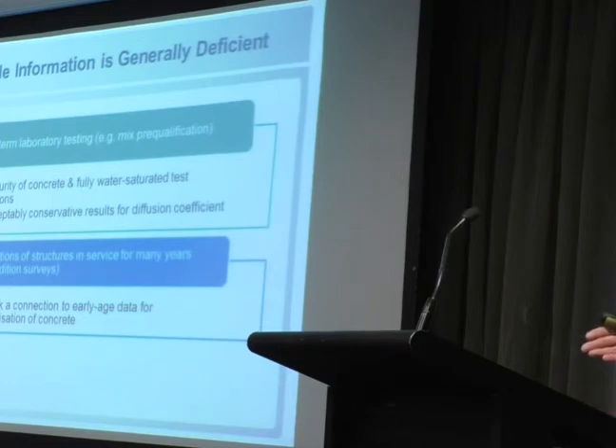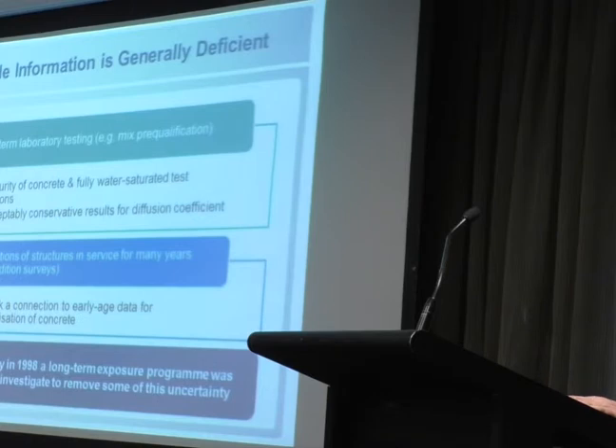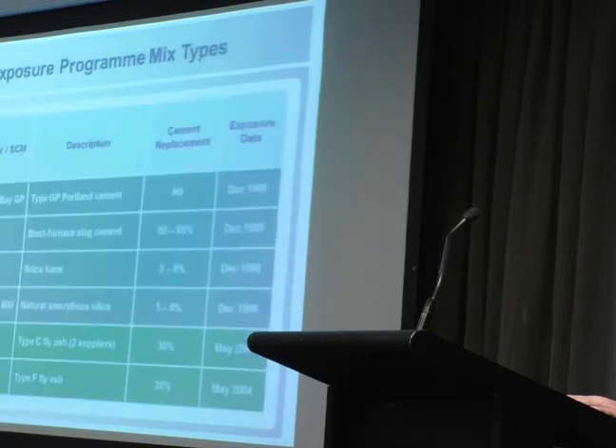We have short-term laboratory tests, typically just 35 days, giving unacceptably conservative results for diffusion coefficients, typically. Or we have profiles measured on structures that are many years old, and it's very hard to relate those one-off measurements to characterization of the concrete that was originally used without spending a lot of time and effort. So consequently, in 1998, a long-term exposure site program was instigated to investigate some of these uncertainties.